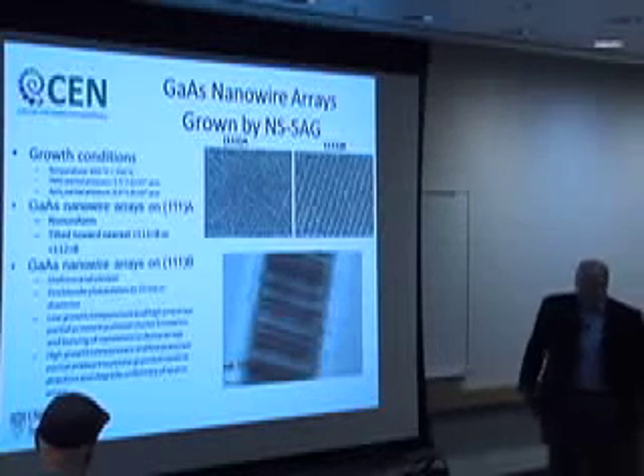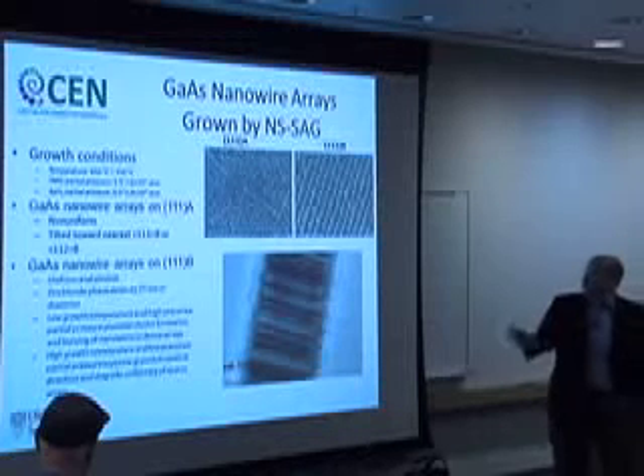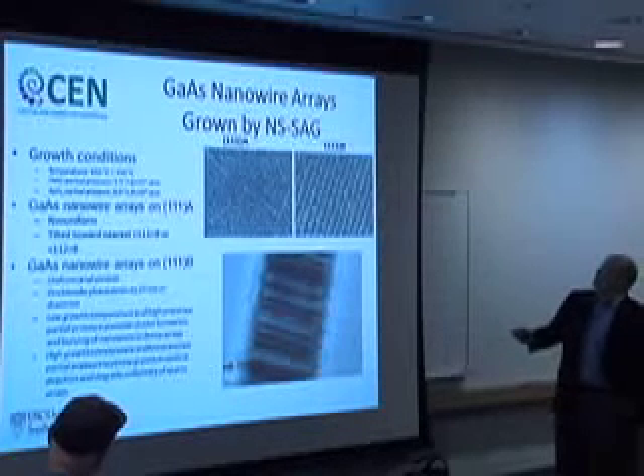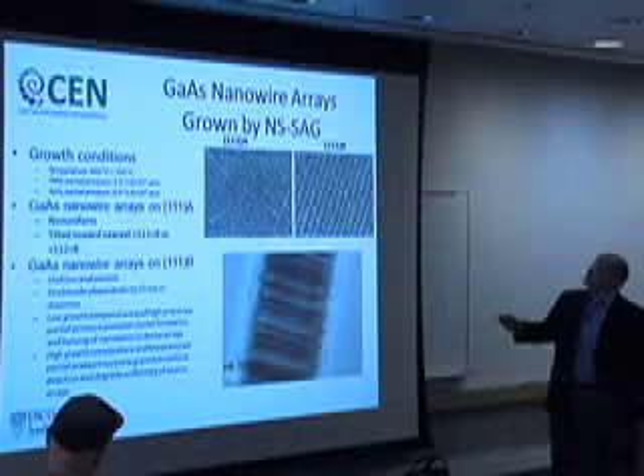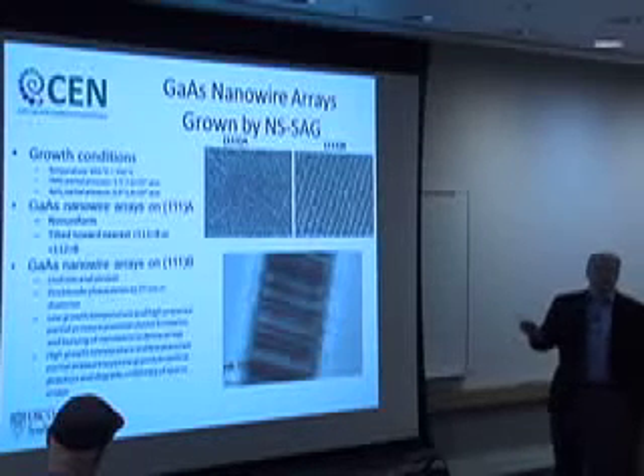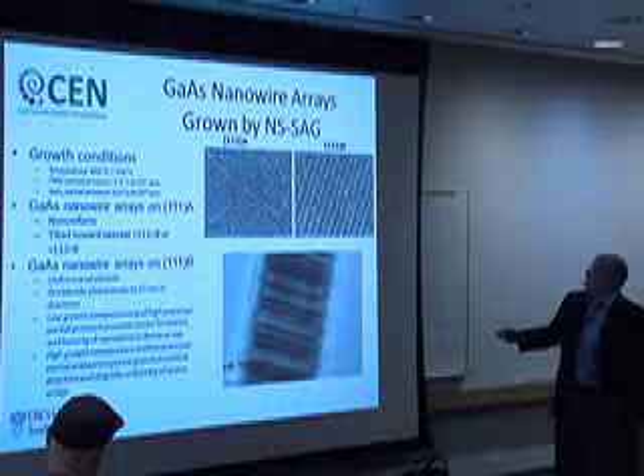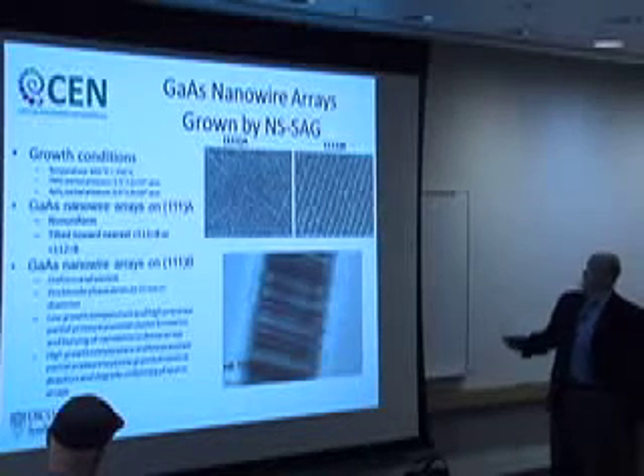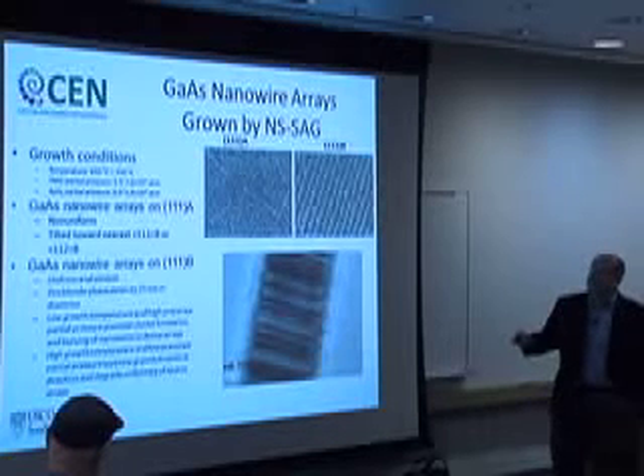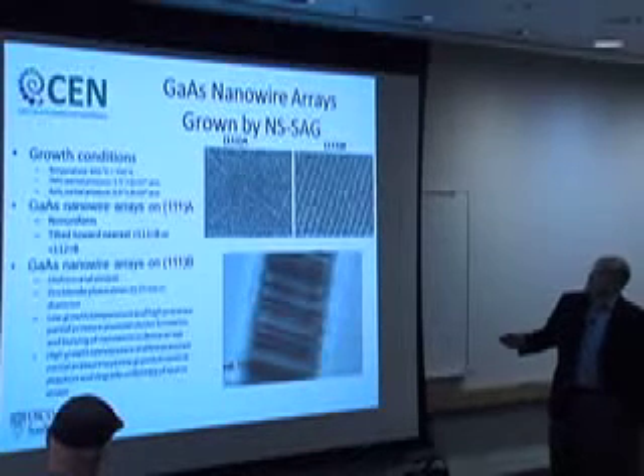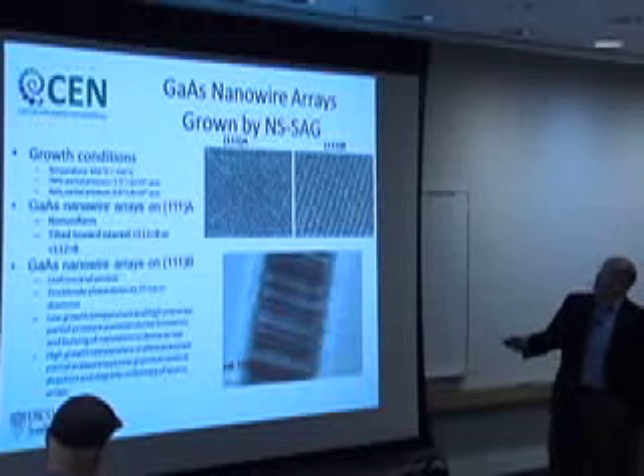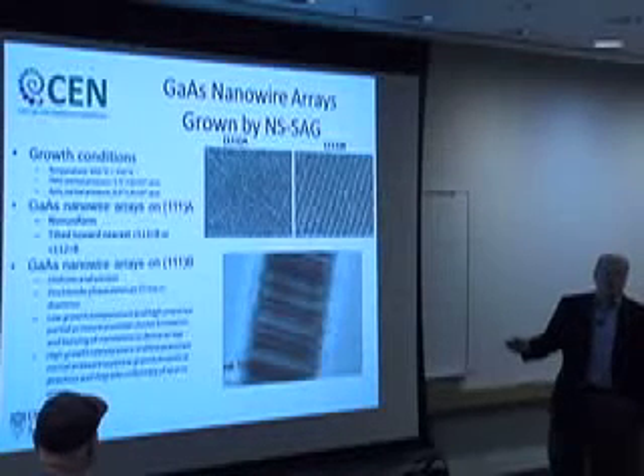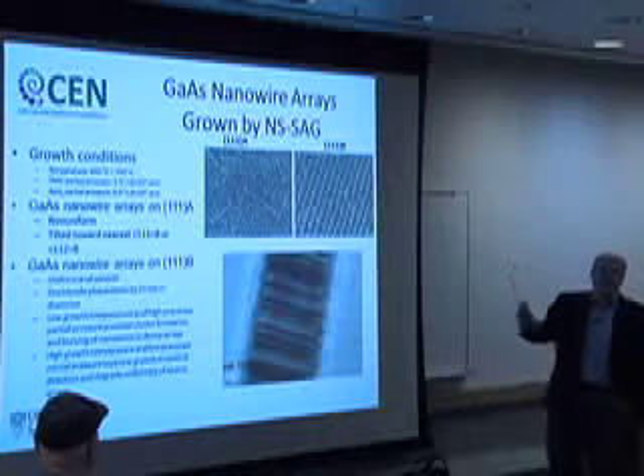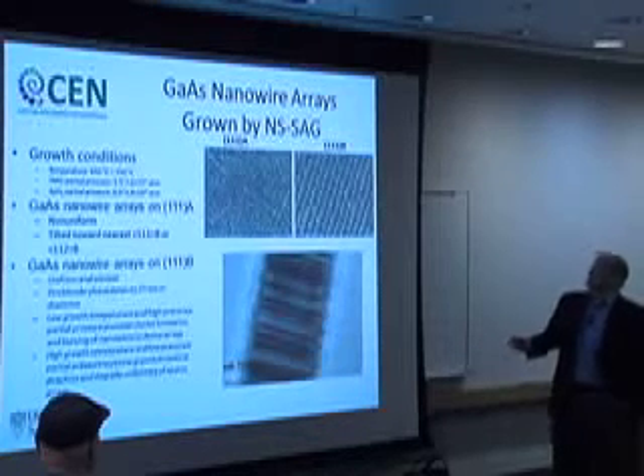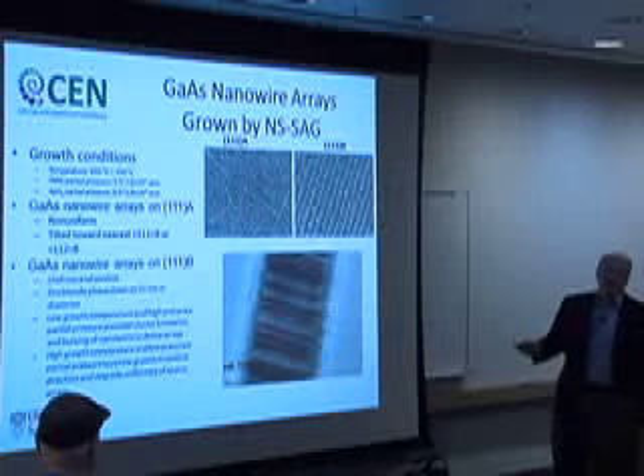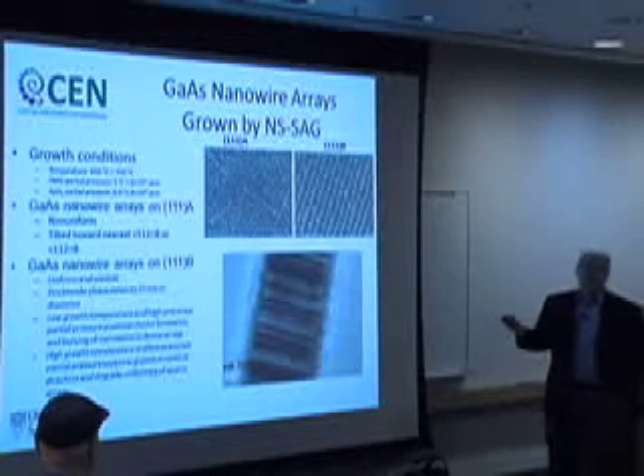Okay, so let me show you what happens, just with a brief picture, when you grow gallium arsenide on a 111A surface and a 111B surface, where we've patterned the surface with openings. On the B surface, we grow a regular array of very nice nanowires, whereas on the A surface, we grow nanowires, but they grow off at angles, and they actually pick up the 111B direction in the crystal. Now, you see lots of stuff in the literature that looks like that, but I like the look of that, so we focused on that.